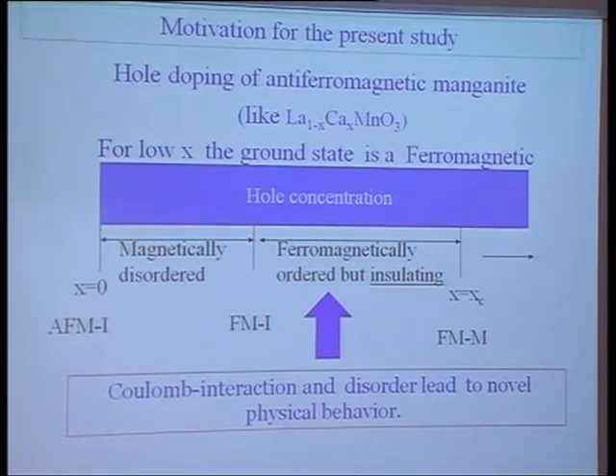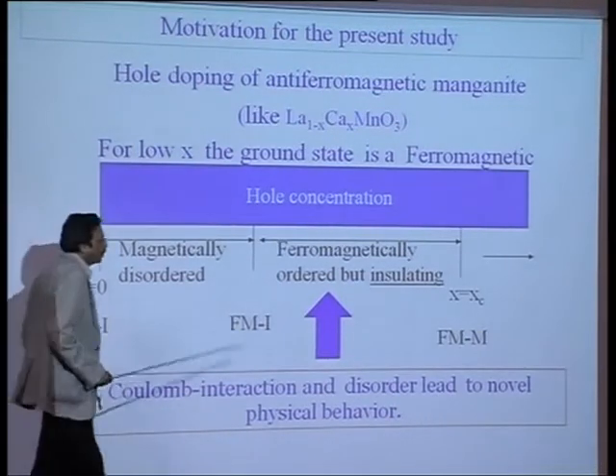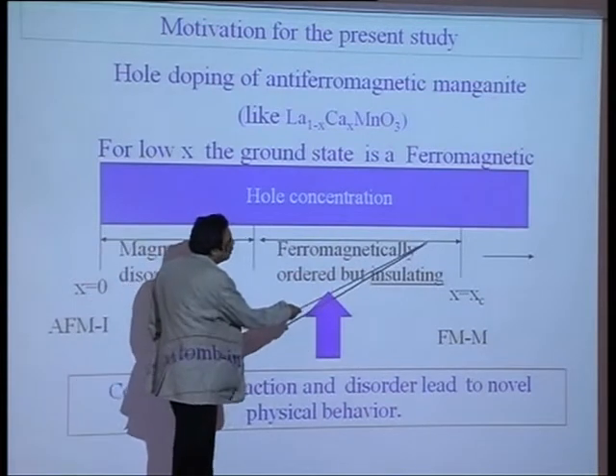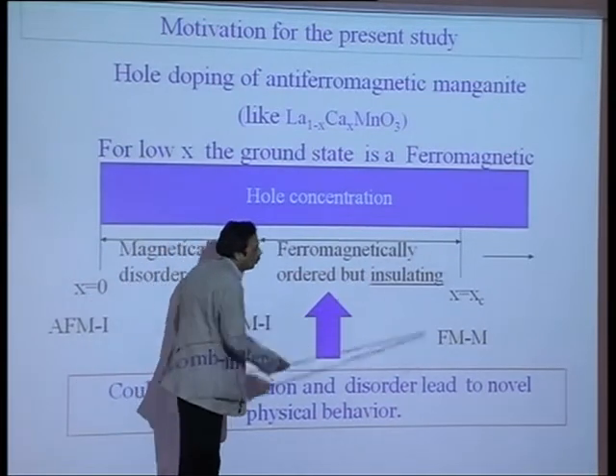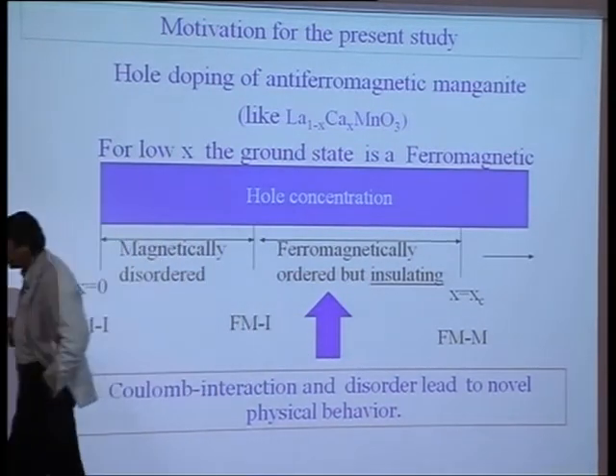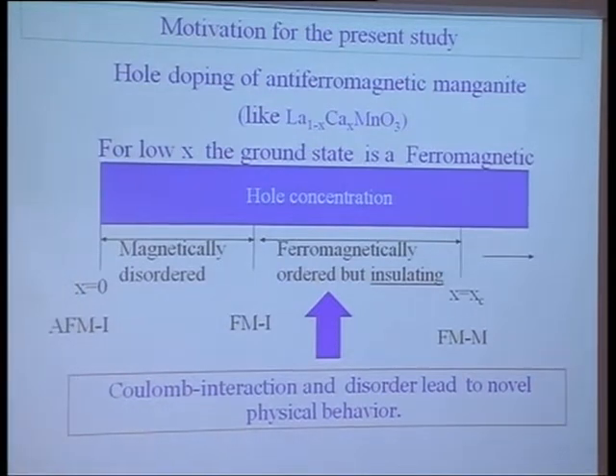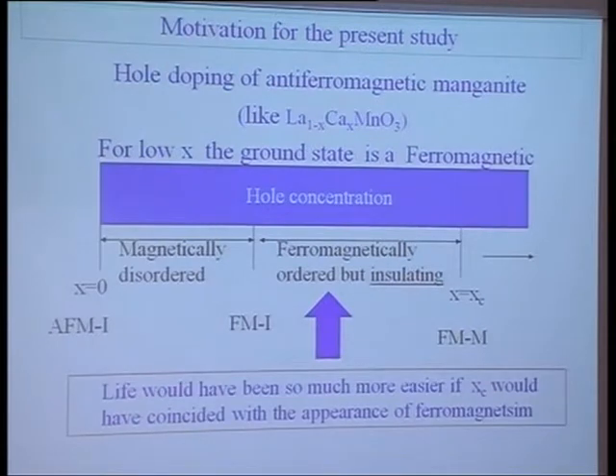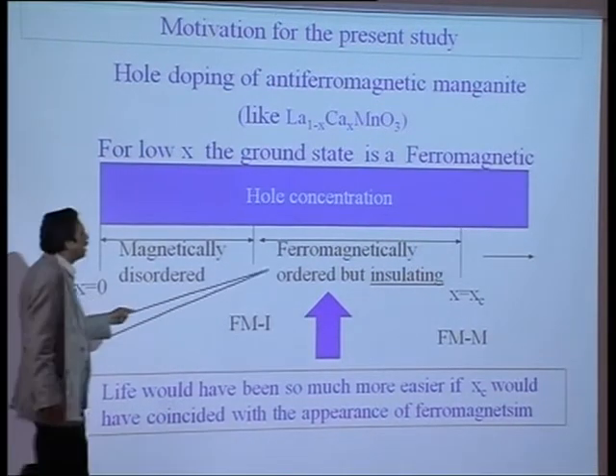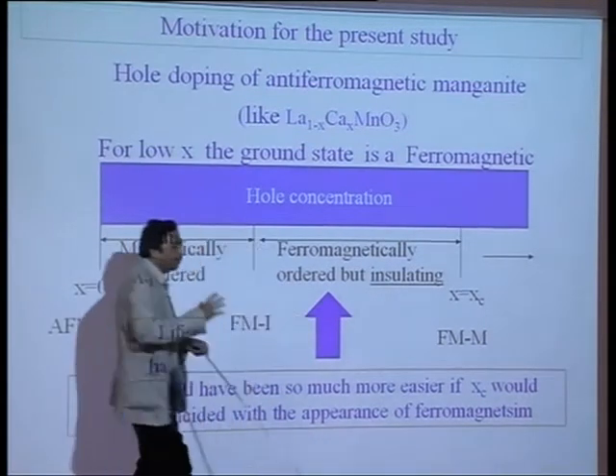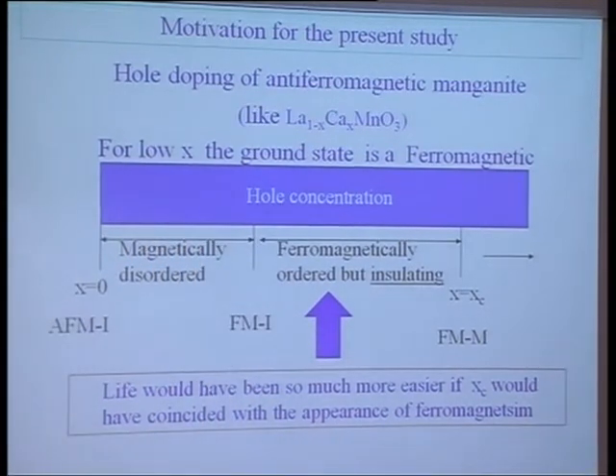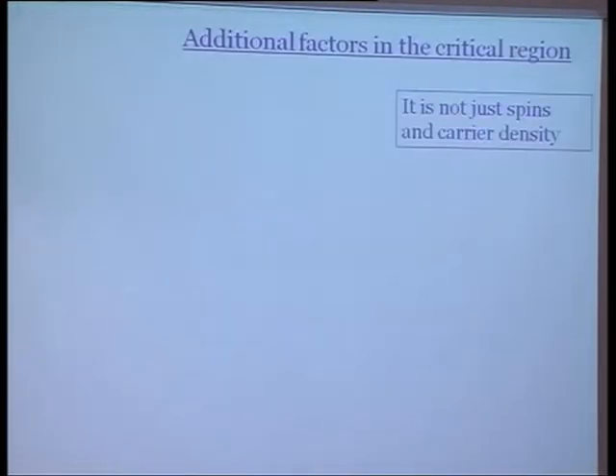Now again, if I borrow the language of the phosphorus-doped silicon kind of thing, the experiments that we'll be doing over here will be around 0.9 of the critical concentration or 0.85 of the critical composition, and try to see what happens. But life would have been much easier if these two points had collapsed. That is, the point where it has become metallic is exactly where it has become ferromagnetic. But unfortunately, it doesn't happen. That's why all of us are employed.